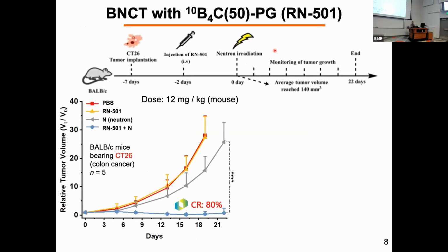This is the most fascinating result, obtained by using 10B-enriched boron carbide nanoparticles. Of course, the surface was functionalized with a very good hydrophilic polymer, polyglycerol. We call this material RN501, where RN is our company name, Radio Nanotherapeutics. This drug was injected into the cancer mice intravenously, from the tail vein, and from the injection to the irradiation we allowed 2 days.